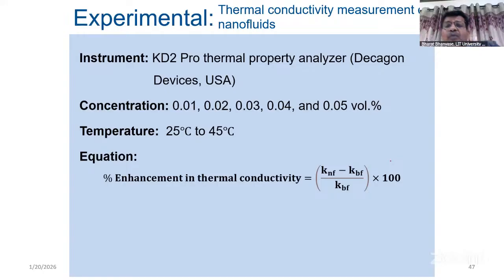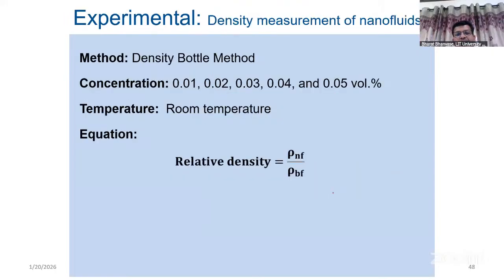For thermal conductivity, we used a thermal property analyzer for measurement at different concentrations: 0.01, 0.02, 0.03, 0.04, 0.05 volume percent, with temperature varied from 25 to 45 degrees Celsius. Percent enhancement in thermal conductivity was calculated as thermal conductivity of nanofluid minus thermal conductivity of base fluid, divided by thermal conductivity of base fluid - that is the simple relation used for the calculation.